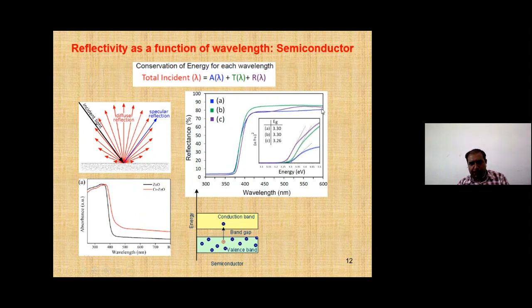If you look into this particular graph in detail, you will realize that when the energy of the incident photon is small enough, the reflectance is very large. And as soon as the energy of the photon is very close to the energy band gap of this particular material, at the same point the reflectivity drops drastically. There is a sudden drop in the reflectivity, and this is a really important message of this particular experiment.